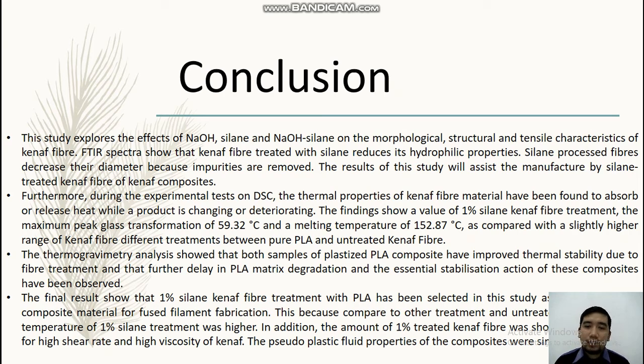Okay, for the conclusion. Okay, this study explored the effect of NaOH and silane on the morphology, structure, and tensile characteristics of the Kenaf fiber. Spectra show that Kenaf fiber treated with silane reduces its hydrophilic properties. Silane processed fibers decrease their diameter because impurities are removed. The result of this study will assist the manufacture of silane Kenaf fiber for Kenaf composite. Furthermore, during the experiment test on the DSC, the thermal properties of Kenaf fiber material have been found to absorb and release heat while the product is changing or deteriorating.